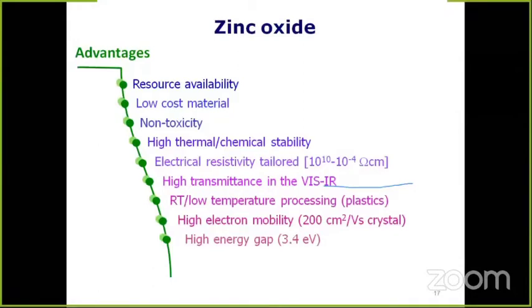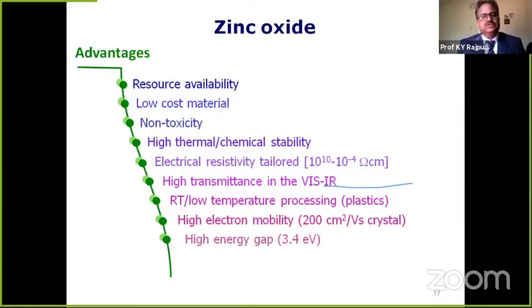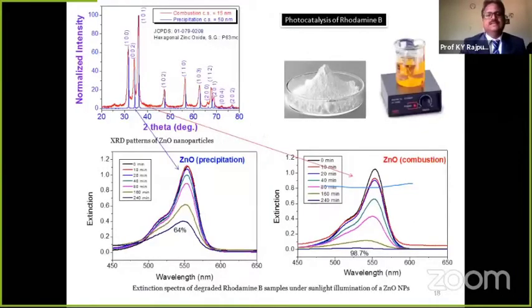Now, zinc oxide, as I said, is abundantly available, not costly, not toxic, highly thermally and chemically stable, and we can tailor its electrical resistivity. They are highly transparent and have other properties. Therefore, these are suitable alternatives to TiO2 for photocatalysis. Therefore, we prepared zinc oxide polycrystalline powder and zinc oxide nanocrystalline powder. Nano means the particle size is less than 100 nanometers. In this case, the particle size of the precipitated powder was 50 nanometers, and the particle size of the zinc oxide powder prepared with the combustion method was 15 nanometers.